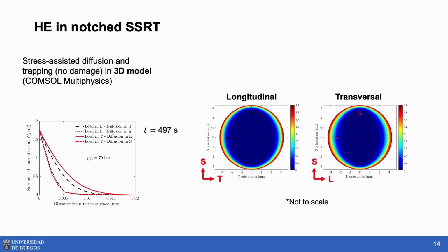You can see here that the penetration distances between L and T are not very different, because you have to think that the penetration distance is proportional to the square root of the diffusivity. So the increase in penetration distance, depending on the orientation, will be proportional to the square root of the tortuosity.